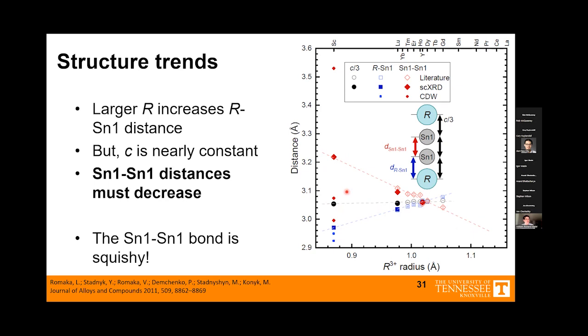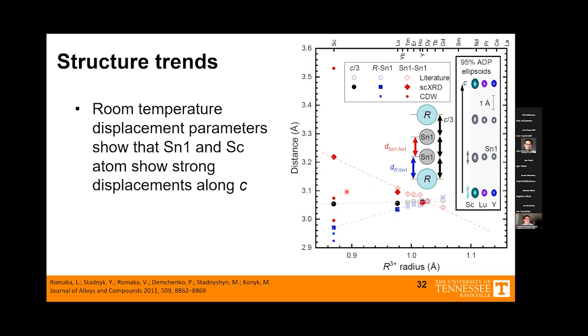The tin-tin bond is already squishy. That's critical. We can see that because as we put those bigger atoms in, those bonds get closer. And that squishiness means that there's room in this column of atoms for displacements. And we see those displacements. They show up in the diffuse X-ray scattering that Stephen and other groups have presented. And we see it in diffraction even at room temperature.